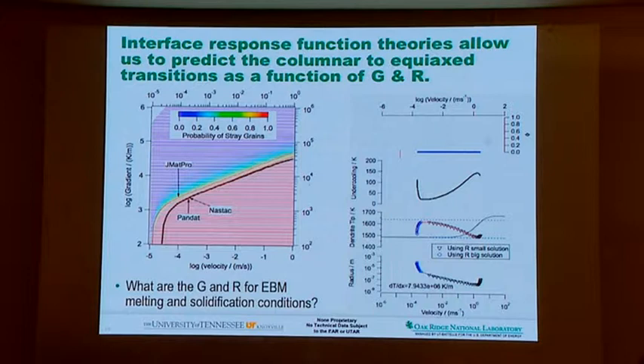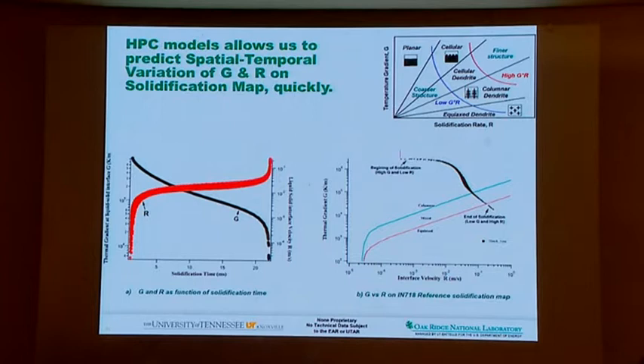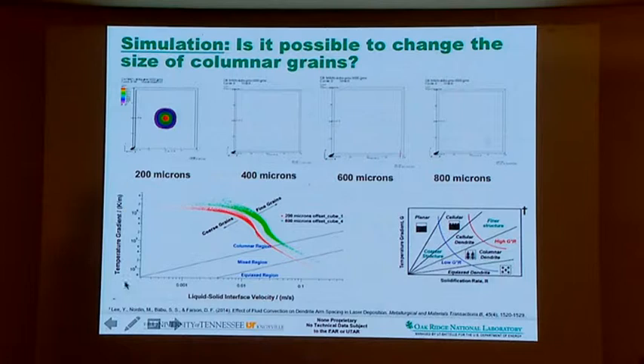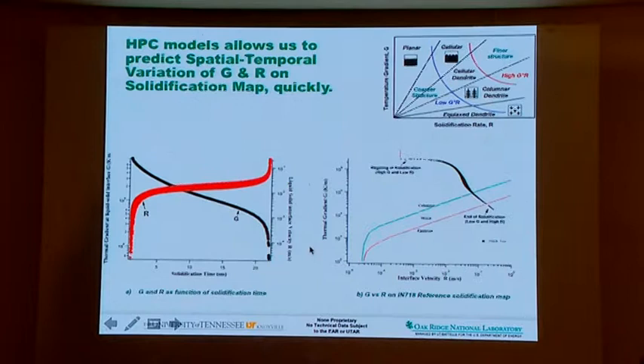When it is collapsing, initially the velocity is zero, because you have a balance between heat coming in and heat going out. Then when the energy goes out, the velocity is accelerating, and the liquid-solid interface velocity can span many orders of magnitude. That's what's shown here. You can see your y-axis is the thermal gradient, and the x-axis is the liquid-solid interface velocity. Wait, I had to go back. Here you can see that the velocity actually increases rapidly towards the collapse of the melt pool.